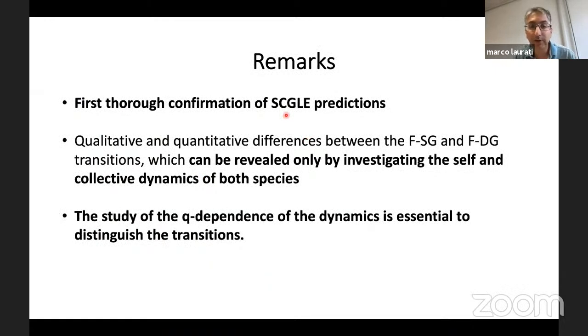So with this, a few remarks on this study, which I think was the first really thorough confirmation of the prediction of the self-consistent generalized Langevin equation theory developed by Magdalena's group. Our study shows that there are indeed quantitative and qualitative differences in the transition towards these two different glass states of the system, which can only be revealed if one can investigate selectively the dynamics of each one of the species in the system. The study also revealed that the Q dependence of the dynamics is essential to distinguish between the transitions.